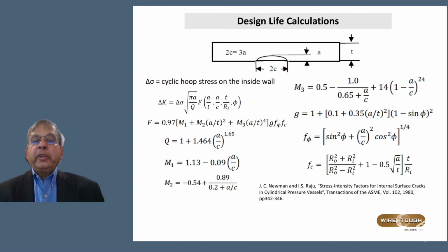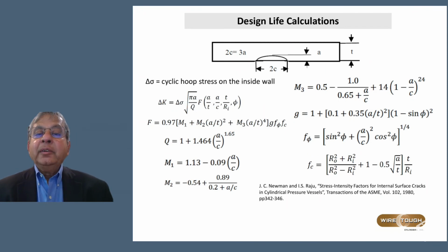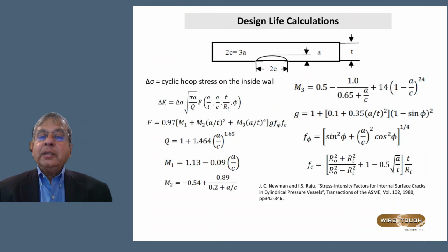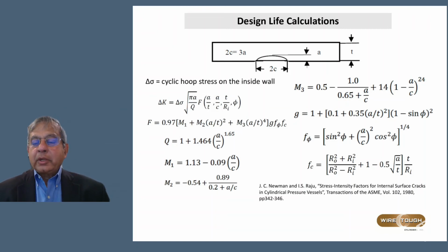The life, we have noticed, is dictated by a surface flaw in the main body of the liner, and we assume a surface flaw size that is equal to the size that is 100% detectable from the ultrasonic techniques used to detect flaws. And this slide basically shows some of the equations that are used for calculating the stress intensity parameters for these types of flaw shapes and geometries.